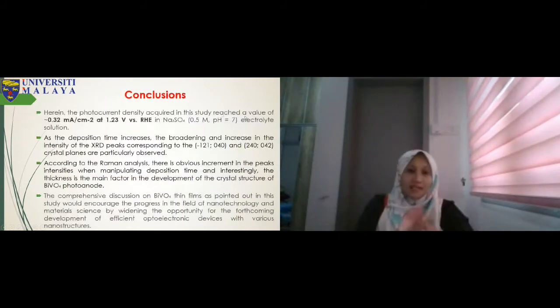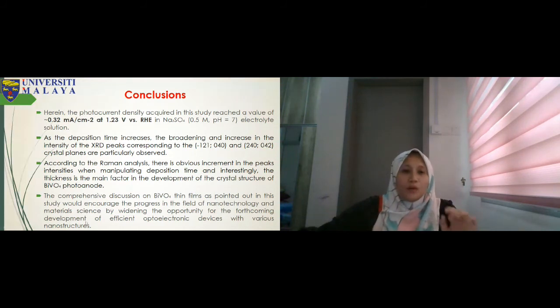Okay, for the last, the conclusion. The photocurrent achieved here is around 0.32 milliampere, using Na2SO4 as electrolyte, as deposition time increases. We can observe, based on the XRD and also according to Raman, an obvious increment in the peak intensity when we manipulate the deposition time.